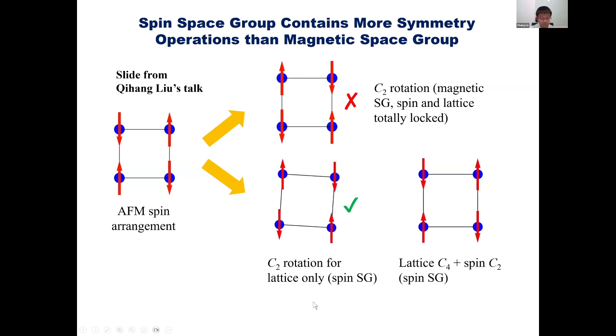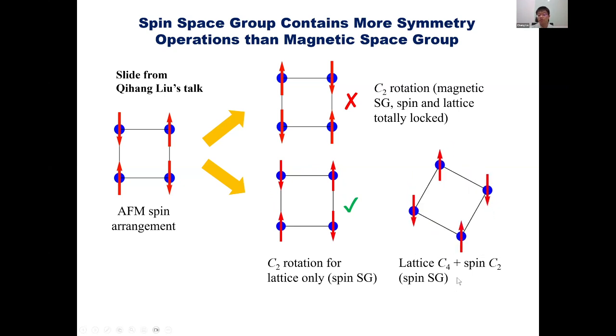in the spin space group, we have several operations that can describe the symmetry of this system, like the C2 rotation of the lattice only, keeping the spin unchanged. And then we have another type of operation, which is the lattice C4 rotation plus the spin C2 rotation. So we do a 90-degree rotation of the lattice first, and then a 180-degree rotation of the spin. Well, for some reason, this is not 180 degrees. That's okay. This operation contains separate rotation angles for the lattice and the spin, and allows for the spin splitting in antiferromagnets.